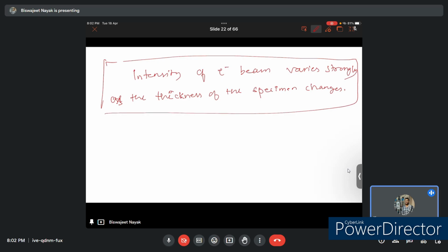So how to measure this intensity? What we are going to do is, inside a crystalline material, think of it in terms of Bloch waves, because only certain wave propagation vectors are allowed in infinite periodic structures.